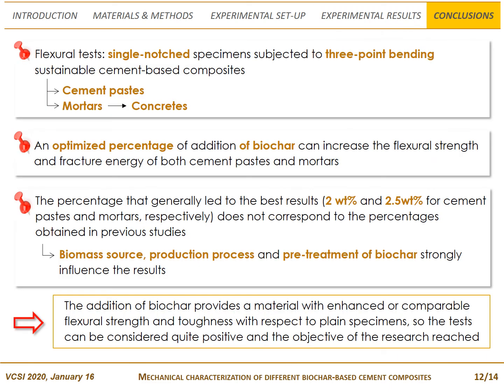Moving to conclusions based on the experimental results, it can be observed that the addition of biochar can increase the flexural strength and fracture energy of cementitious composites. In this study, the percentage that generally leads to the best results is 2% for cement pastes and 2.5% for mortars. These values do not correspond to the percentages found in previous studies, but this could be related to the different production process of biochar and to the biomass source.